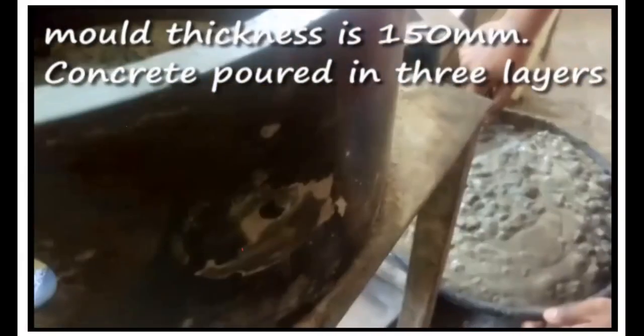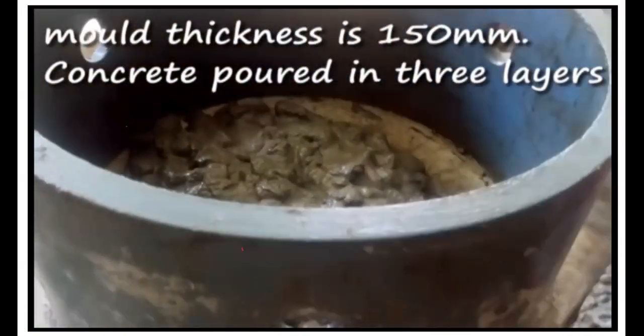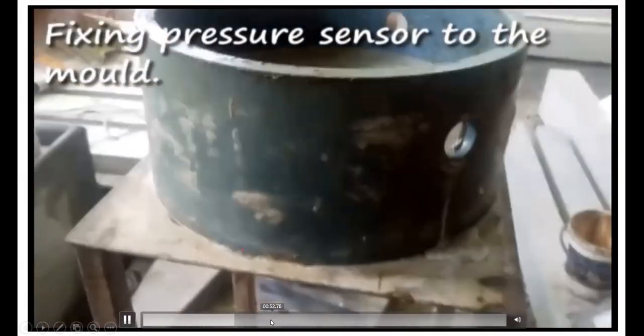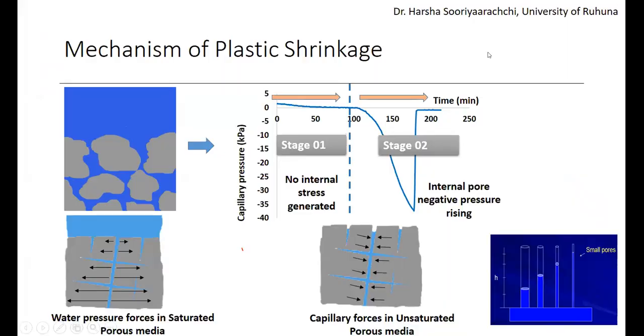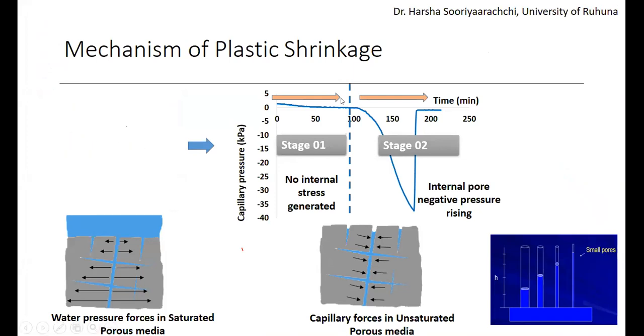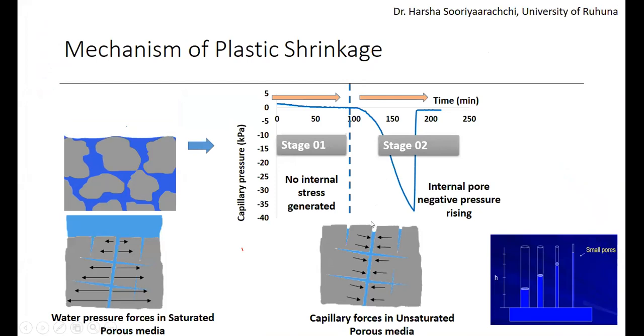Then pressure monitoring was done to identify how the pressures change and what the capillary pores are doing in that process, as I have shown previously during the video. With the changing of the bleeding and the evaporation, it was identified that the capillary pores generate more negative pressures. It generates some suction with the formation of the meniscus. There will be some surface tension. With the surface tension, there will be a tendency towards crack formation on the surface of concrete. So the smaller the pore sizes, the more negative pressure, and the risk of shrinkage cracking will be higher because of the higher negative capillary pressure. So if we can change the capillary pressure, then we can avoid the plastic shrinkage cracking.